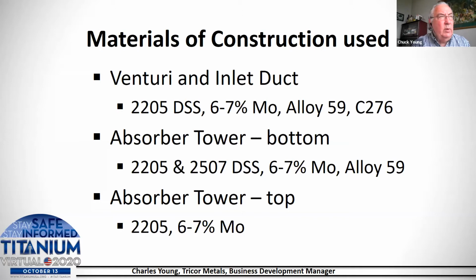Some 6 or 7% moly like AL6XN or 254 SMO. Some alloy 59, which is almost equivalent to like 625, and then C276. And one thing to point out here is that most of these materials of construction have been determined either in Europe or Asia. Very little of this is done in the United States. So that's why the alloy 59 is very prevalent here. The top of the absorber tower is normally 2205 or the 6 to 7% moly.